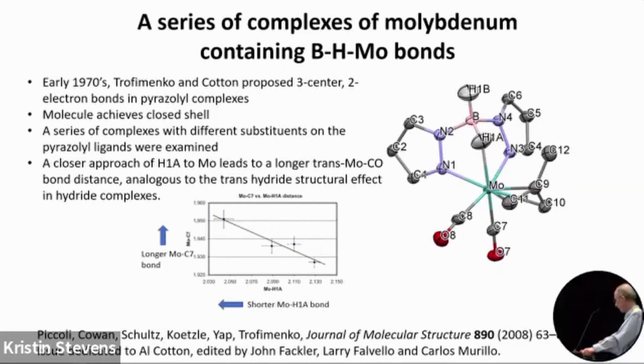And we collected data on 4 molecules. The analysis was done by John Cowan and Paula Piccoli. And one of the findings was that a closer approach of H1A to the metal, that is, as this bond gets shorter, this bond gets longer. And that's shown here in this plot. And so this is similar to, or analogous to, what we see in other hydride complexes. The trans hydride structural effect is observed in these compounds.